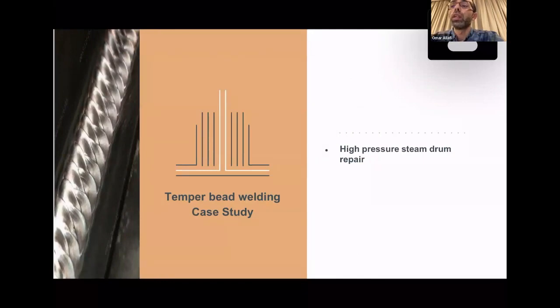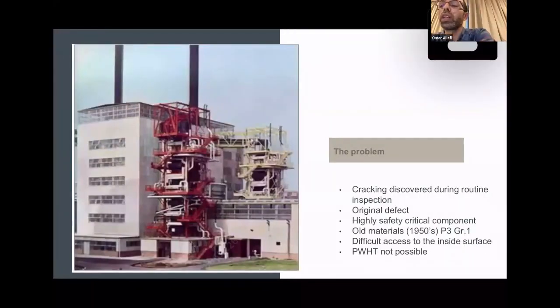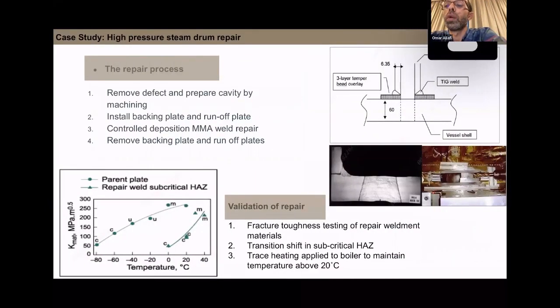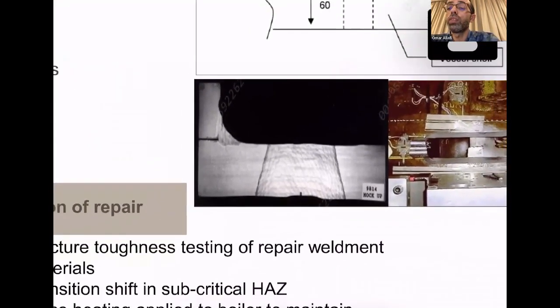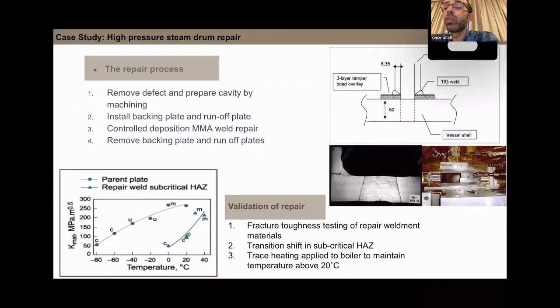The temper bead welding case study: I will share one case study where cracking was discovered during routine inspection. This is inside a steam drum. The material was old, from the 1950s. It was difficult to access on the inside surface, and PWHT was not practical. So what they did was remove the defect, prepare the cavity by machining, and install the backing plate and runoff plate. They controlled the deposition using SMAW weld repair, and then removed the backing plate and runoff plates. They qualified the test coupon. This is the test coupon qualified, and this is the geometry of the weld.